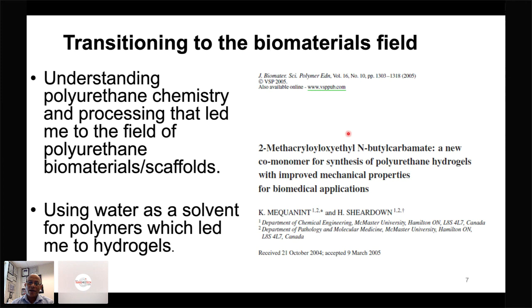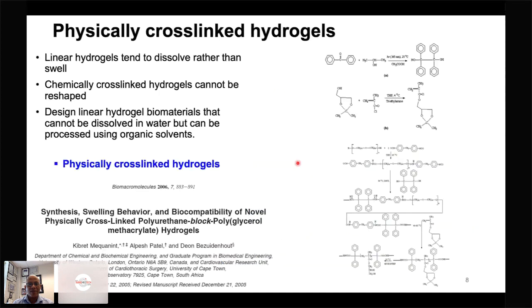Then the idea when we started working with these particular hydrogels was that this specific combination of butyl carbamate monomer with hydroxyethyl methacrylate would give us a hydrogel that is as good as a cross-linked hydrogel, but it was not chemically cross-linked. It was in fact physically cross-linked. So we went into this area of physically cross-linked polymers, and then we continued to work in this physically cross-linked hydrogel field for a while, maybe for about 7 or 8 years after this.